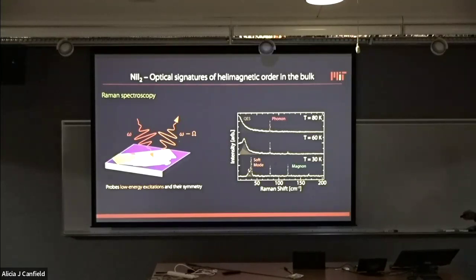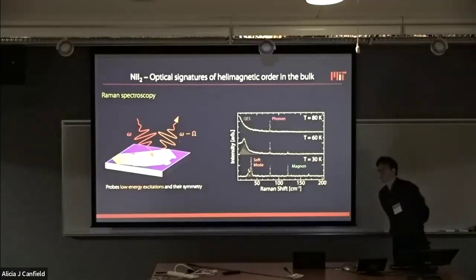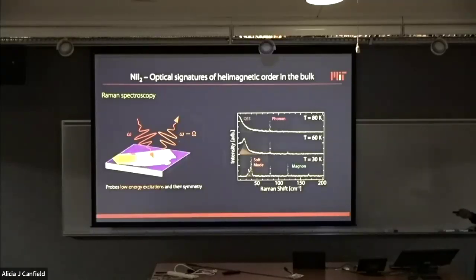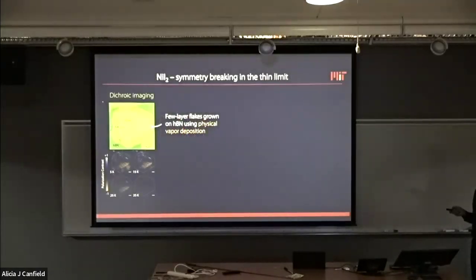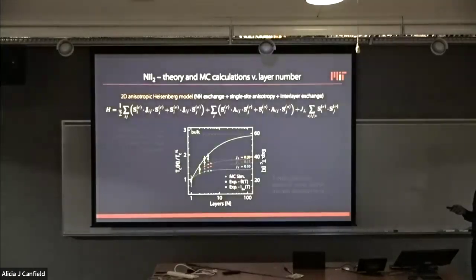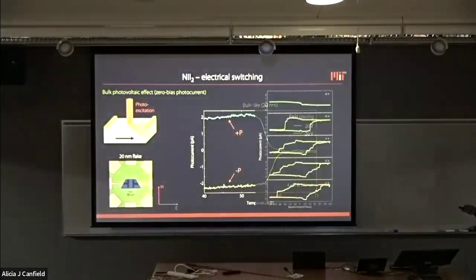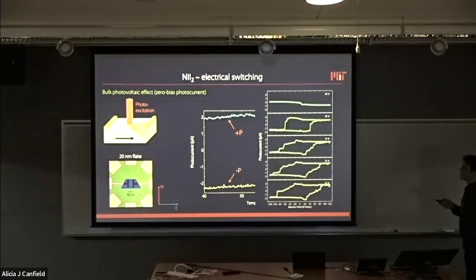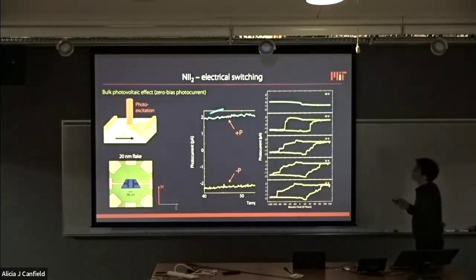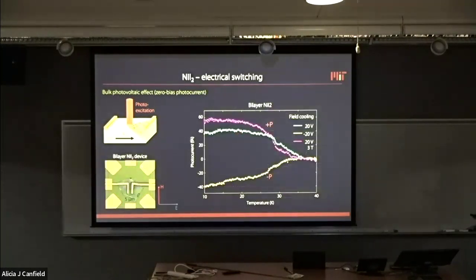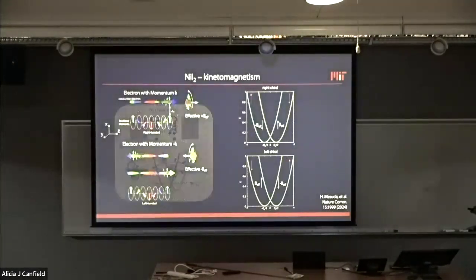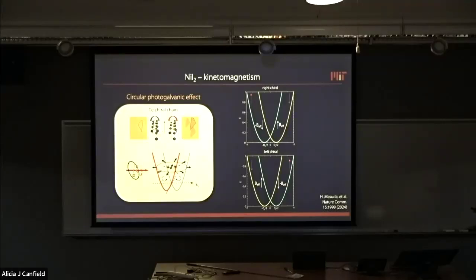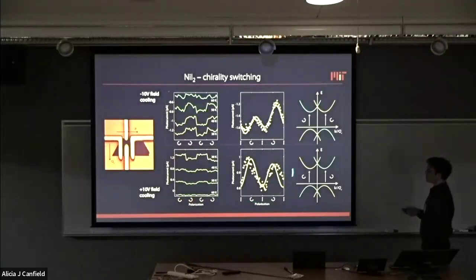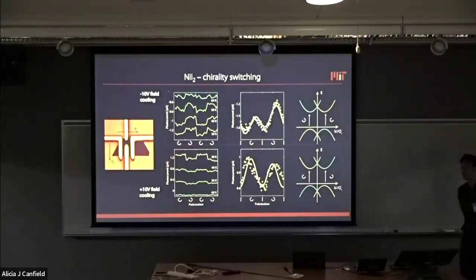Okay, any final questions? Yeah, maybe a quick question. When you measure the photogalvanic response, there's a way of actually extracting the symmetry from the ratio of these response tensors. Are you in fact seeing this twofold symmetry? So is one of the components 0? For example, if you measure along the perpendicular direction, you get 0 photocurrent. Yeah, for example, in this experiment, the linear photogalvanic effect should respect twofold symmetry as well. So we see that twofold symmetry in these experiments. The circular we haven't tried yet. The data that I was showing were literally taken 3 weeks ago, so this is very fresh experimental results. So we're thinking about ways. I'd be very happy. Yeah, let's.